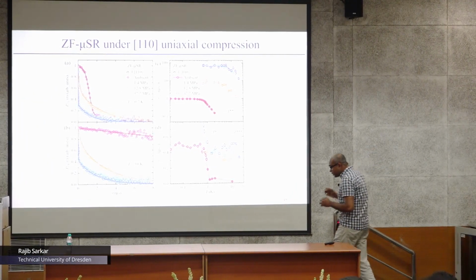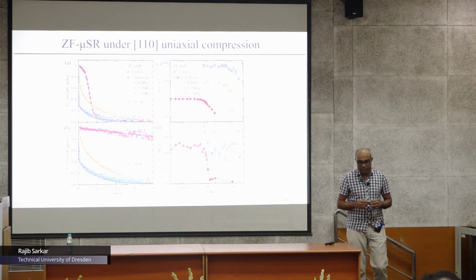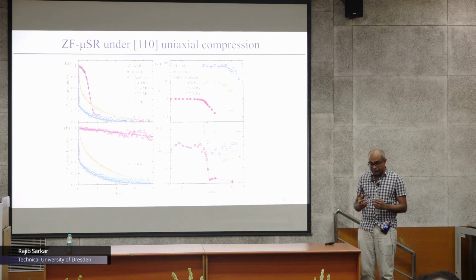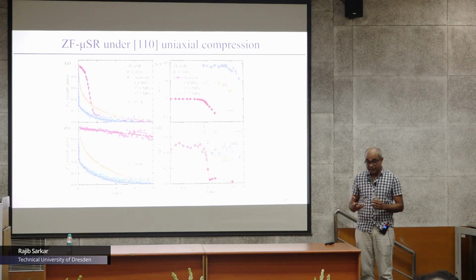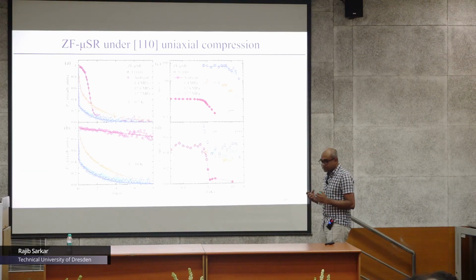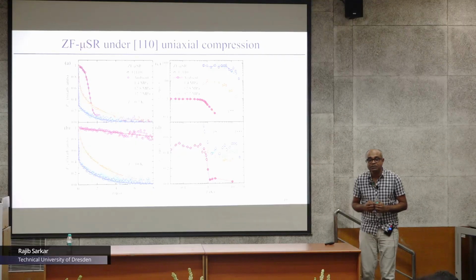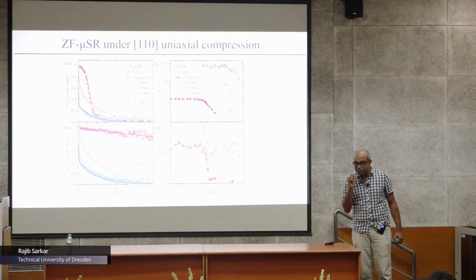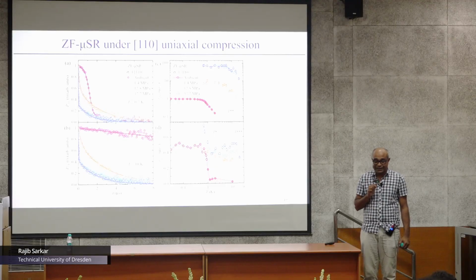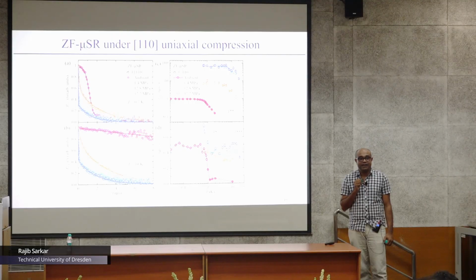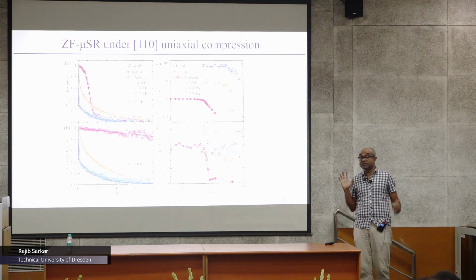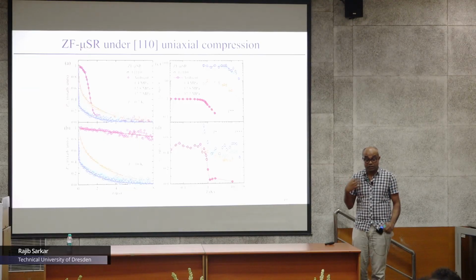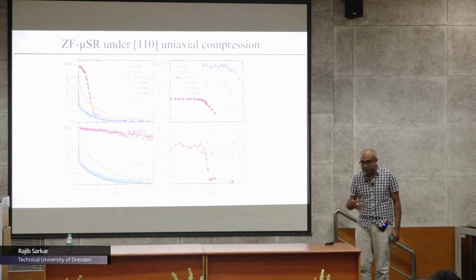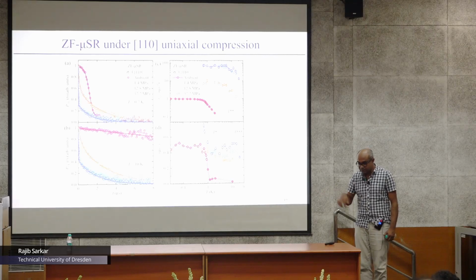But the issue is that, as I already mentioned in the last slide of my talk, on the basis of the experimental data we believe that we have a strong coupling of the lattice and the spin degrees of freedom. If there is strong coupling of the lattice and the spin degrees of freedom, then the muon would see it, right? Because the muon does not probe the lattice, but it does probe the spins. So if it is a strong coupling, then it is very hard to avoid. This is what we see for the time being. The idea may change, but for the time being, this is our consensus. This is what we believe.